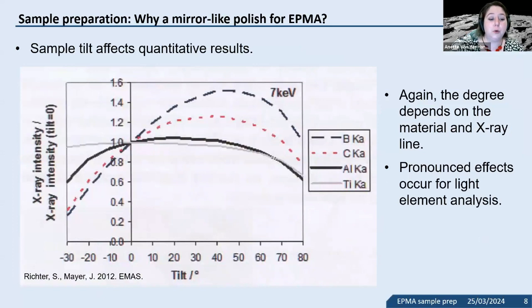Then sample tilt can also be a problem. This is a similar type of graph, where at 0 we have no tilt, and then we have a positive tilt and a negative tilt relative to our standard, and here is the X-ray intensity ratio. This would be an untilted sample, and here we see a couple of very light elements, which usually have very low energy X-rays that get easily absorbed, versus titanium K alpha. Titanium K alpha needs a significant tilt to show a reaction, but an element like boron, carbon, and eventually aluminum can see a 50% increase or an 80% drop. That's the range that we see here. So very pronounced effects, specifically for light element analysis.